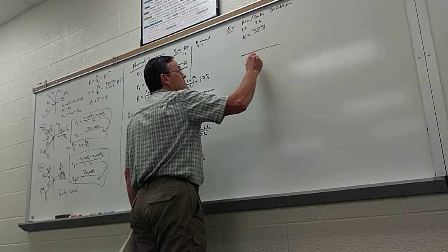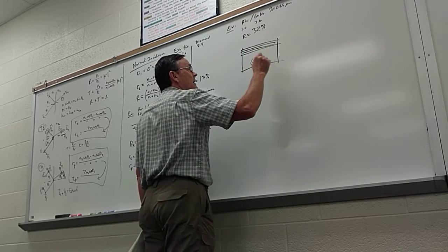And then remember we talked about how lasers work? So for a laser, you always have to have optical gain, and you need feedback for a cavity. And so we talked about how you can take a gallium arsenide wafer, grow some epitaxial layers on it, and then cleave it, and then you have a nice crystallographically flat surface.